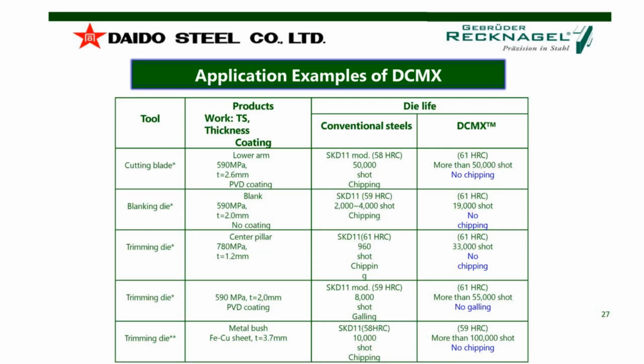Now we have an overview of different applications. They all work in the same way. We have in the first line a cutting blade, then a blanking die, and then 3 trimming dies. The strength was in the first line about 590 megapascal, and in the middle, the center pillar was about 780, a little bit higher, but a little bit thinner material. The customer was always using D2 grade for the first time: in the first line a modified D2 with 58 HRC, then in the next lines D2 with 59, or for the center pillar, 61 HRC.